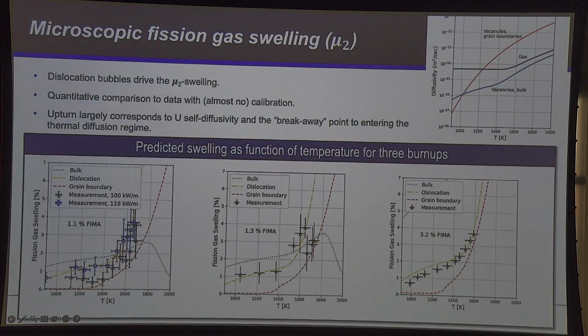And if you look at this swelling behavior, so this is swelling and fission gas release as a function of temperature for different power densities and burn-ups. And again, if you compare this yellow line with the experimental data, we actually capture this behavior pretty nicely. The different curves here represent different populations of gaseous elements. So that means, are they in the bulk? Do they interact with grain boundaries? Or do they interact with dislocations? Where these bubbles are really drives the behavior. Turns out that dislocation bubbles is really important.